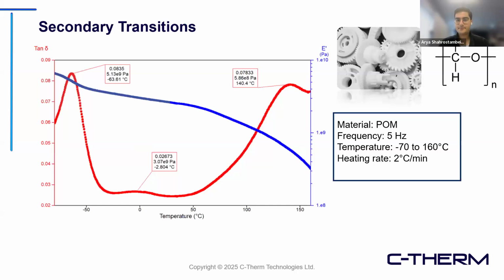So let's take a look at 2 case studies here. So this case used POM, polyoxymethylene, which is a common polymer with applications for gearing or bearing. And so it's really famous for its mechanical strength. So you definitely need high capabilities to test this material accurately, especially for lower temperatures. So as you can see, running a temperature sweep test using a MetroVib DMA can give you the insight at different stages of the transition.